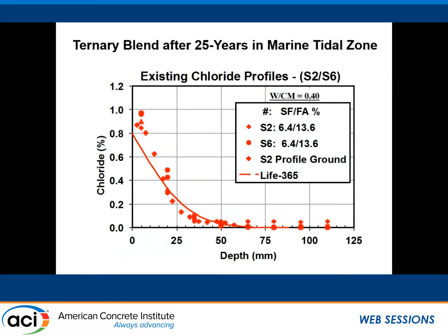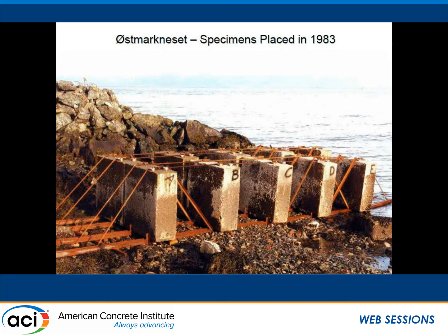And you can see the data points there are the chloride profiles in those blocks at 25 years. And the curve there is Life 365's prediction. So again, Life 365 is actually a really good indicator of what happens under marine conditions. It's not so good for highway structures, I will add that, but marine exposure is pretty good. Just another example of use of Life 365.